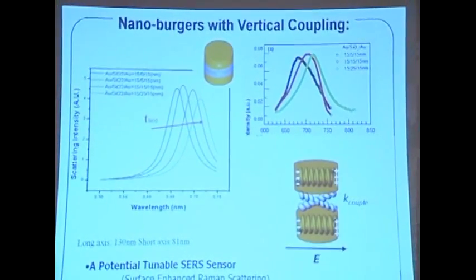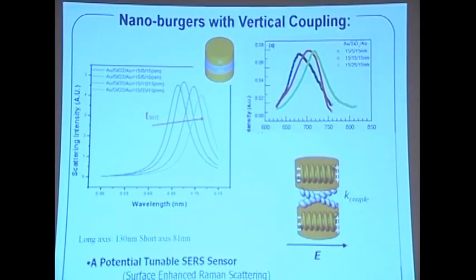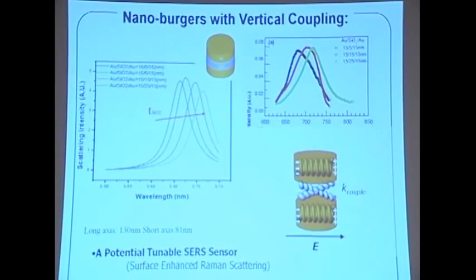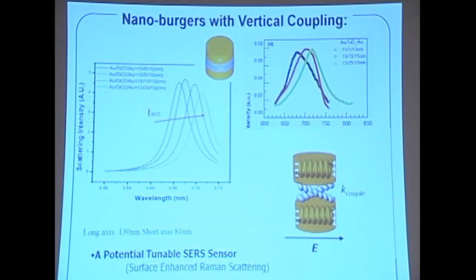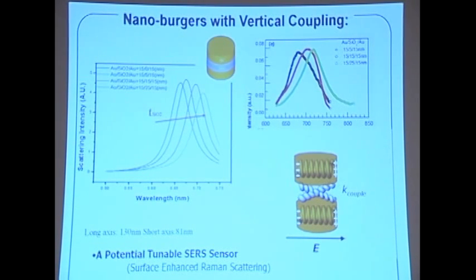However, at the time, I also asked my student whether we could make two nanoresonators with a spacing of a few nanometers. As you know, E-beam is very hard to use to write two dots spaced 2 or 5 nanometers apart. So we decided to stack two resonators on top of each other, using a silicon oxide layer to control the spacing. Silicon oxide today can easily be made 1 nanometer thick as a gate oxide, as the industry does, and even in our microlab you can do a few nanometers. So in this case, we are now coupling the two resonators vertically.